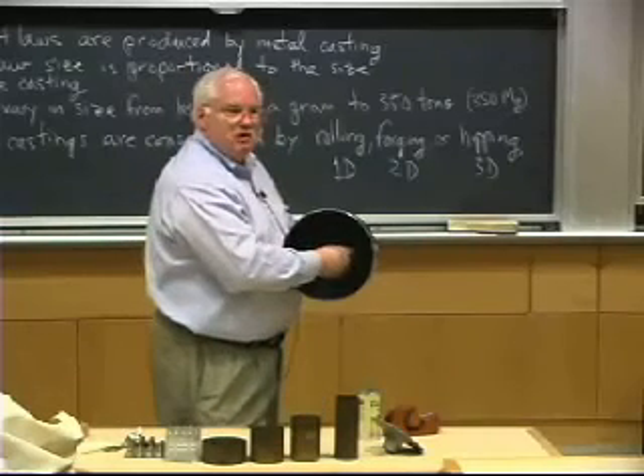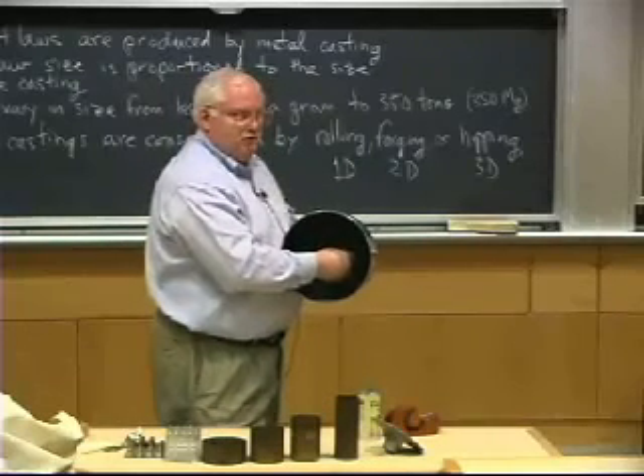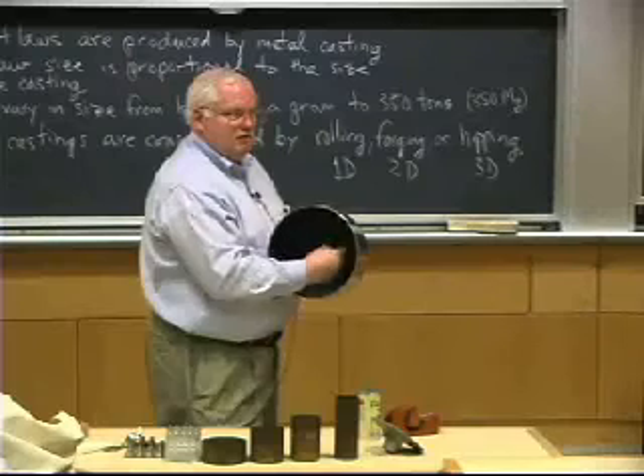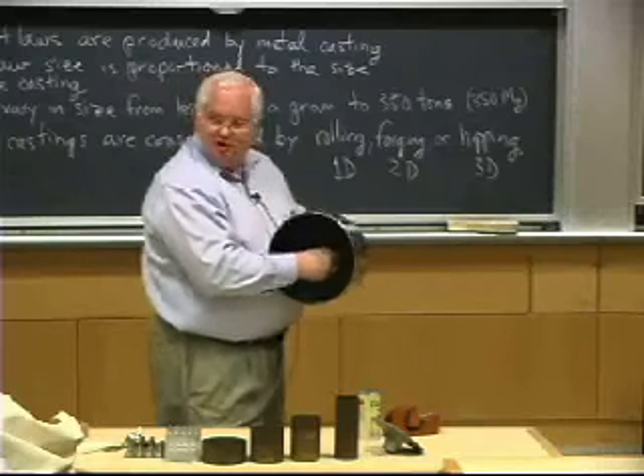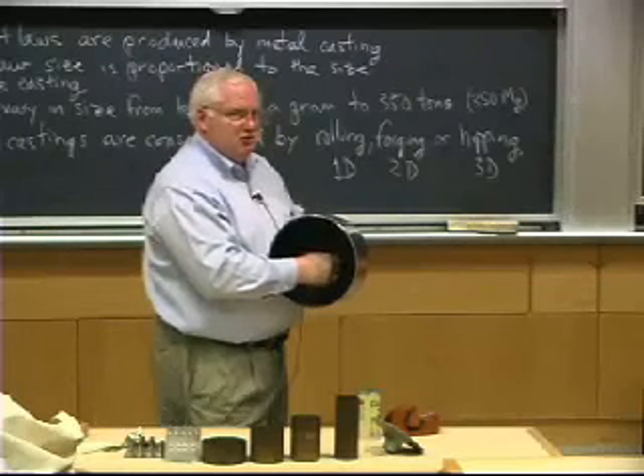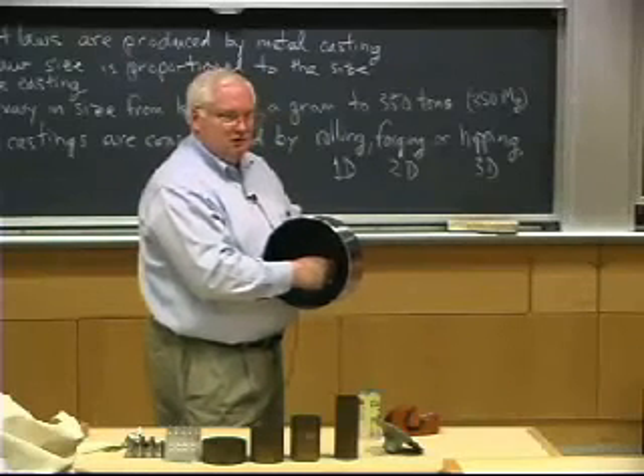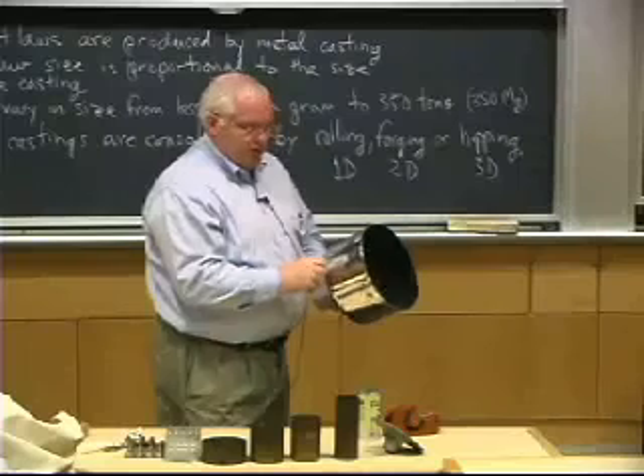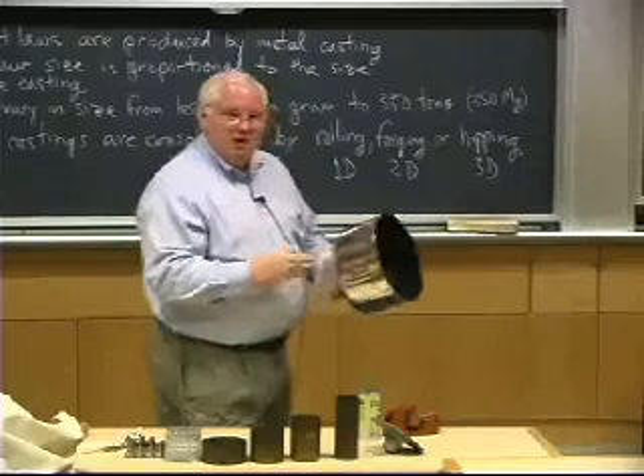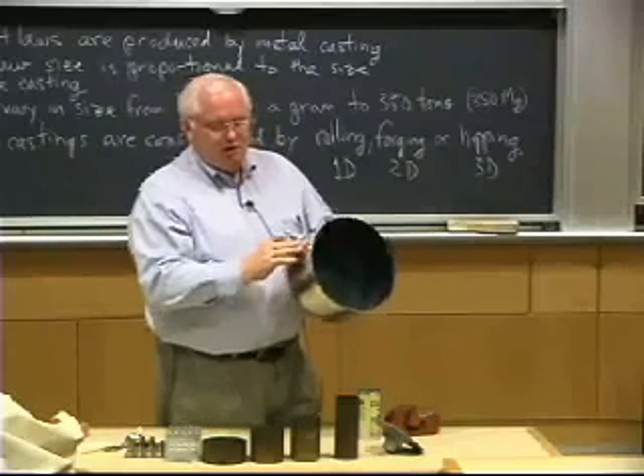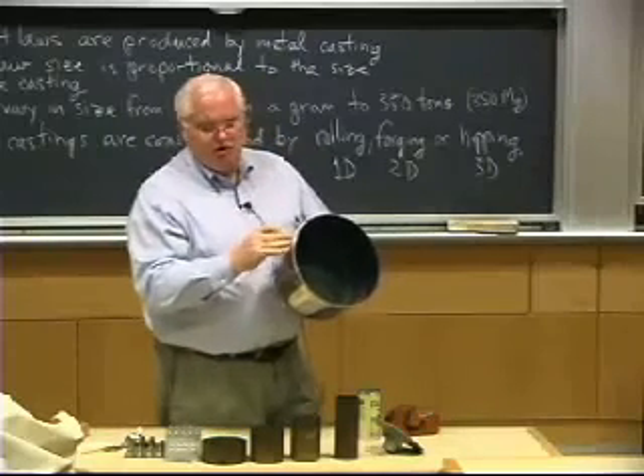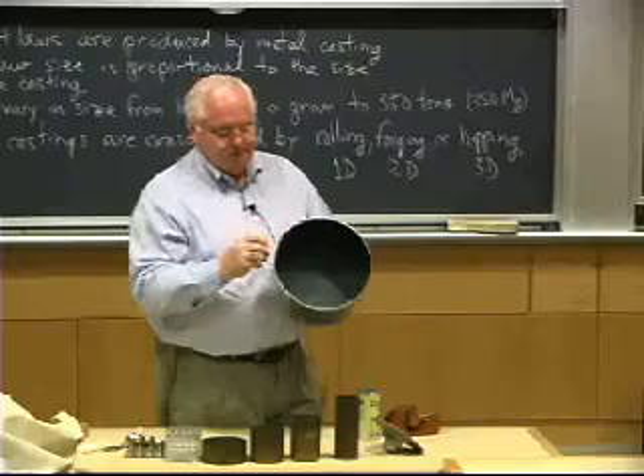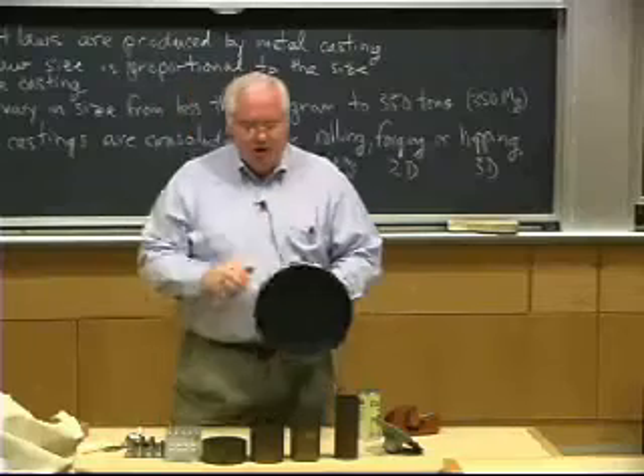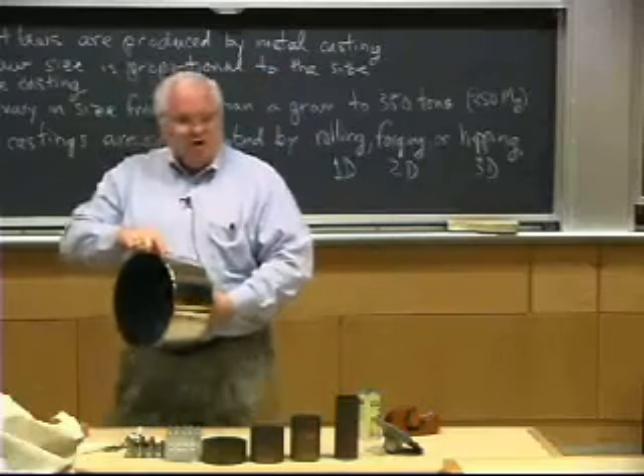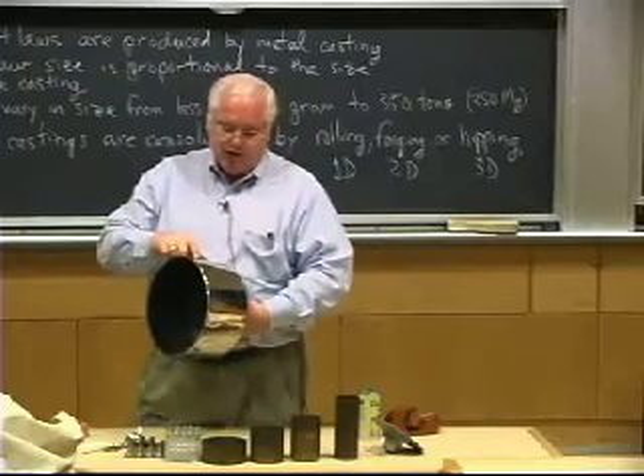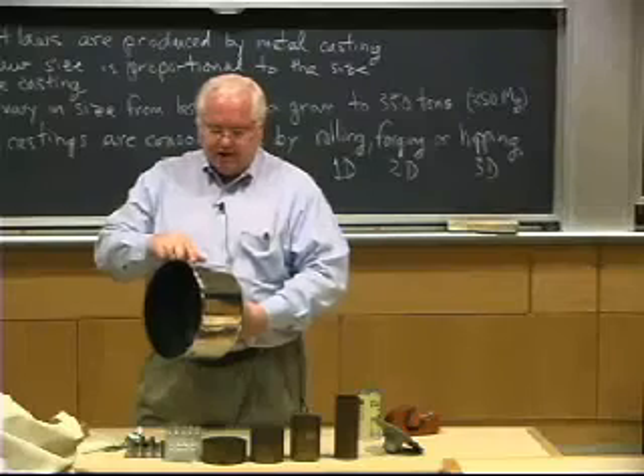Actually, yeah, if you put it on the bottom here, you're going through a little layer of Teflon, but there's almost no magnetism on the bottom because that's the original annealed sheet. It's little, okay? But here there's a little more, and it goes up the side. The more you deformed it, the more it transforms in this martensitic transformation to a ferritic type of, or martensitic type of stainless steel.